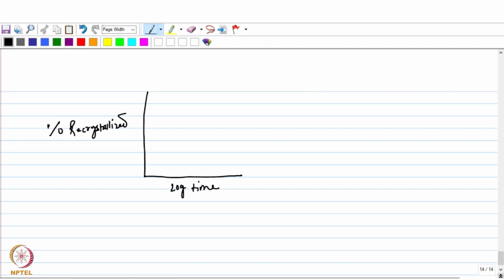And this typically generates an S-shaped curve like this at a particular temperature for a particular material. Okay, and from here also you can again see the effect of the recrystallization temperature. If you do this at different temperatures, you take the same material, deform it to the same level, and then you heat it to different temperatures and hold it for different amounts of time. Okay, so as you increase the temperature, you would find that the time for a particular amount of recrystallization will also decrease.